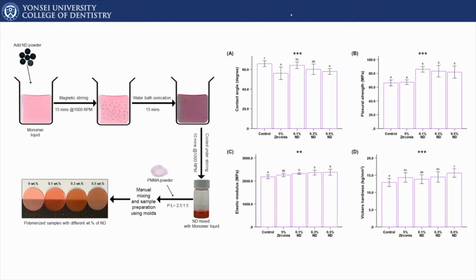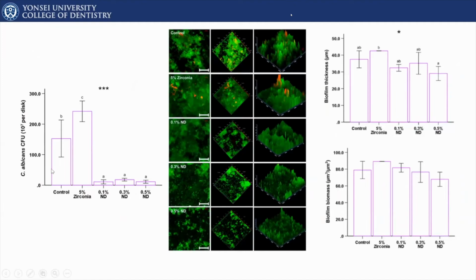First of all, we incorporated it into a monomer liquid of PMMA, which is commonly used for denture materials or orthodontic retainers. As you can see here, it had statistically significant effects on the flexural strength, elastic modulus, and Vickers hardness, and the effects were more significant than zirconia, which is commonly investigated for improving mechanical strength. Not only that, it also had antifungal effects. Compared to zirconia, it shows a dramatic reduction of Candida albicans colony forming units, as well as oral biofilm formation, as you can see here.